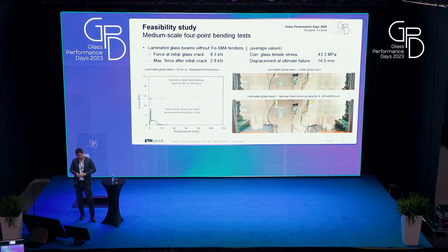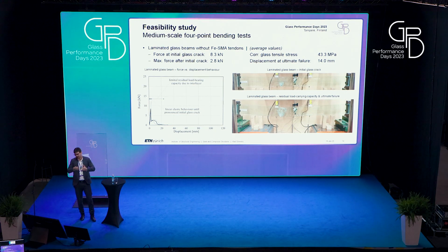However, after this initial crack, the force dropped to around one third, and we were also only able to reach quite low displacements, or small displacements, until the ultimate failure.